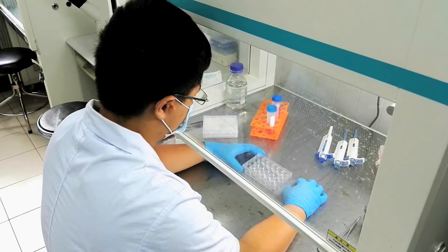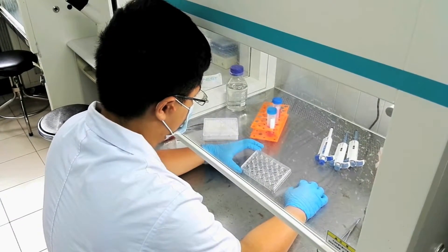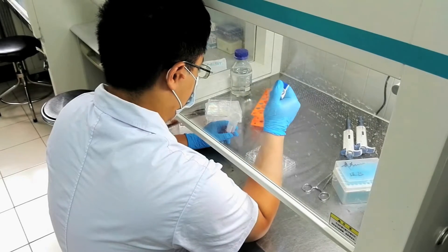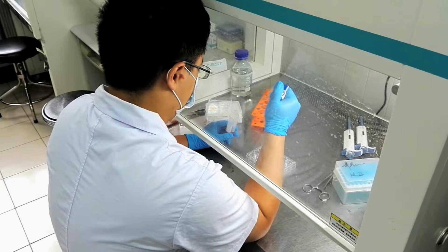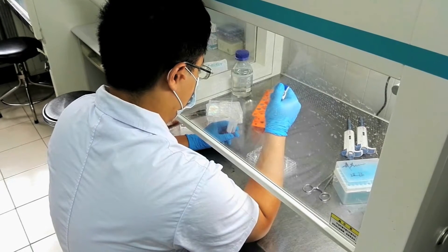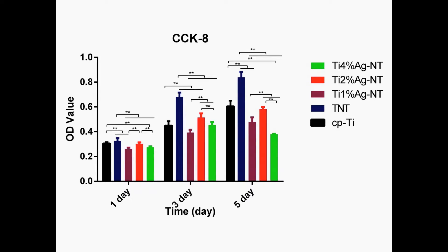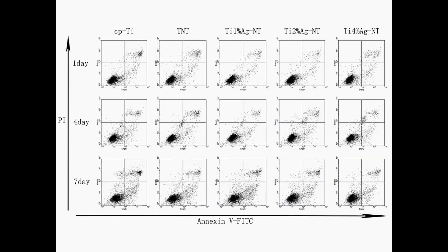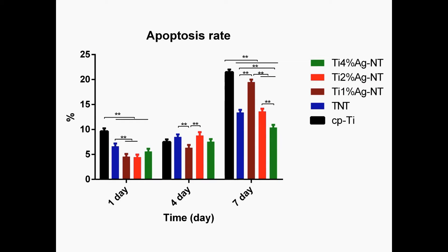The biocompatibility experiments were carried out in the central laboratory of the first affiliated hospital of China Medical University. The results proved that the sample with 2% silver had less biocompatibility than titanium nanotubes, but its performance was satisfactory, as demonstrated by the higher cellular viability and the lower cell apoptosis rate obtained with it, compared with those achieved with commercial pure titanium.